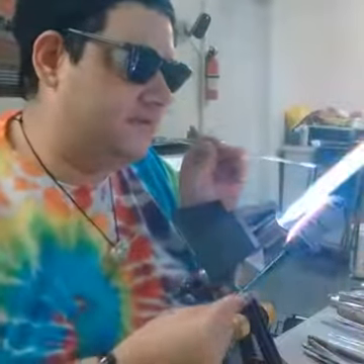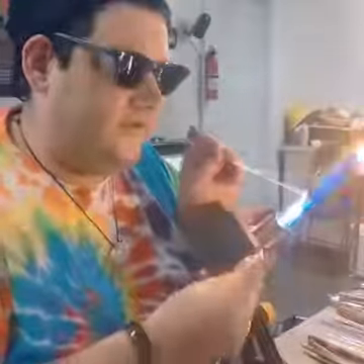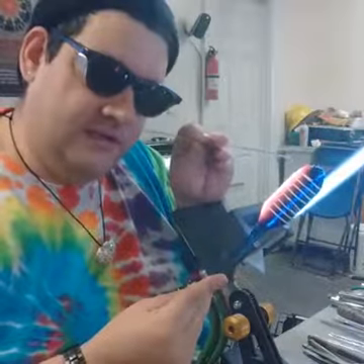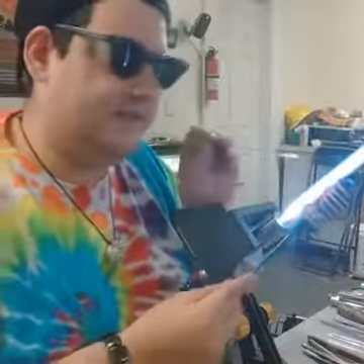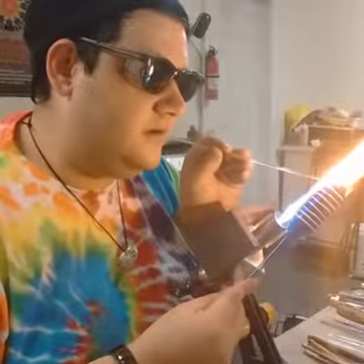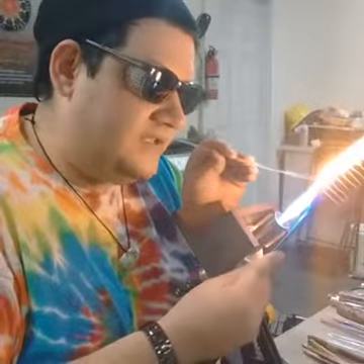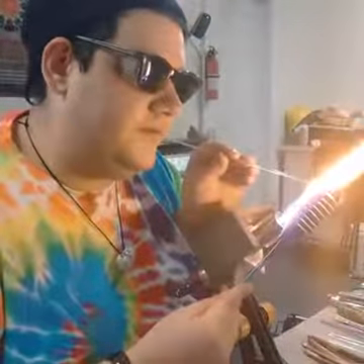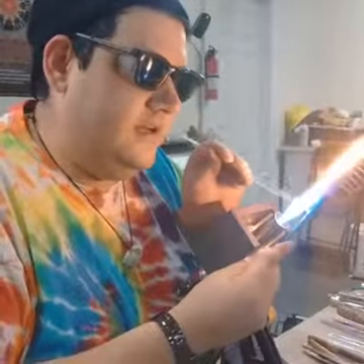The other thing about a wrap and rake is that the flame needs to be hot enough that it melts the wrap that's one ahead of the flame at least. And the way you draw down on it to rake needs to be slow enough that the glass you're trying to rake through is warm enough so that you're not forcing anything. And the converse can be true too. You can get the glass too hot, and if you do that, you start gouging into your blanks.